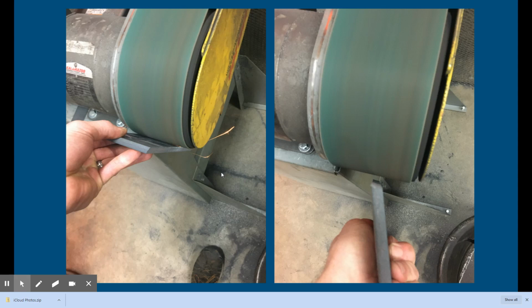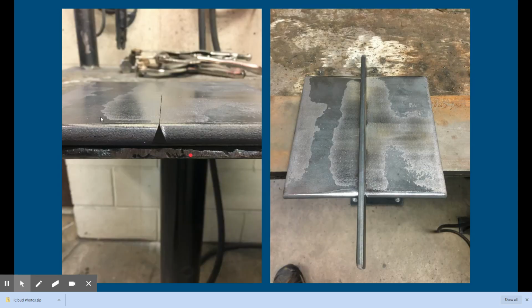Mill scale melts at a much higher temperature than steel. So even though it's a very thin layer, it can cause some problems as you're welding. So since this is a test, go ahead and do it. Put your best foot forward and get that mill scale ripped off. So you can see I set this down on my table, and most of our weld tables have spatter all over them. Yes, the students do try and grind that off eventually, but you can see the table is not going to be very flat. It's not going to be very smooth.